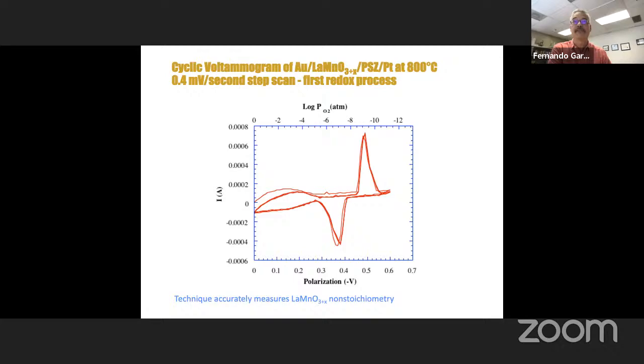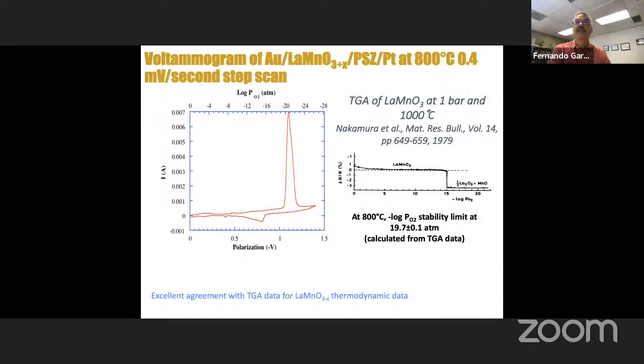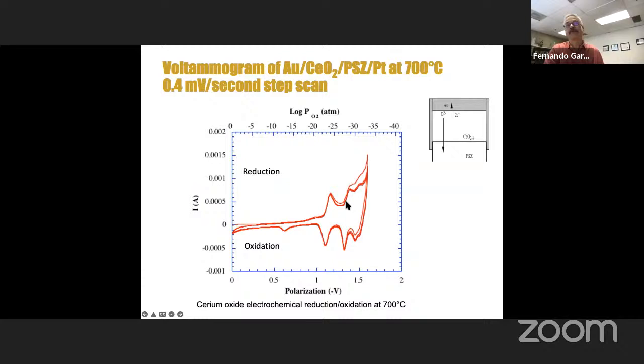Ceria was one of the first ones which we used because, let me go back to the cyclic voltammetry of ceria here, this is beautiful behavior. And this is why it works so well in car catalytic converters, because you can cycle back and forth between supplying oxygen and reoxidation as the stoichiometric ratios change within the catalytic converters of cars. But we've tried mixing ceria with some of our perovskite catalysts, and it seems to promote complete oxidation of the system. Again, we're finding that you need to do the experimental work, as our first principles theoretical predictions on this have not been particularly accurate.